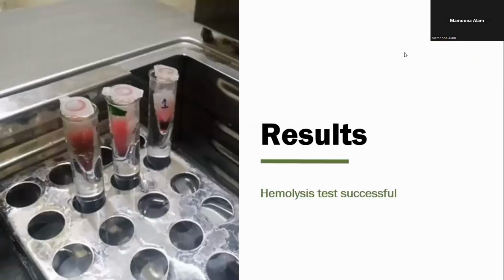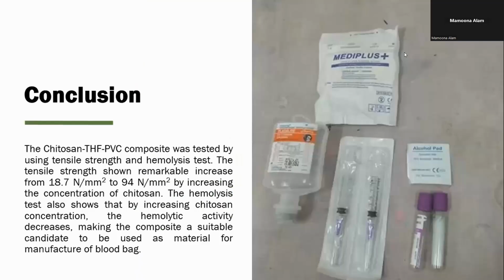My hemolysis test was successful because when I removed the supernatant and immersed the membrane in these test tubes and kept them in the water bath, the blood remained the same. Even after 7 to 8 hours, I did not see any changes in the blood.